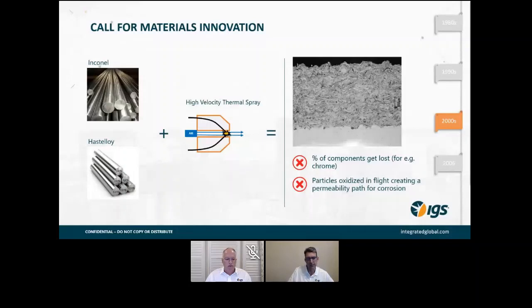So as an example, in an oil and gas type application, an alloy, Hastelloy C276, was a typical material going into the spray gun to be sprayed in the field. Well, as it turns out, although you put a Hastelloy C276, just as an example, into the thermal spray system, what you get out is not a Hastelloy C276. So the thermal spray system changes the material.